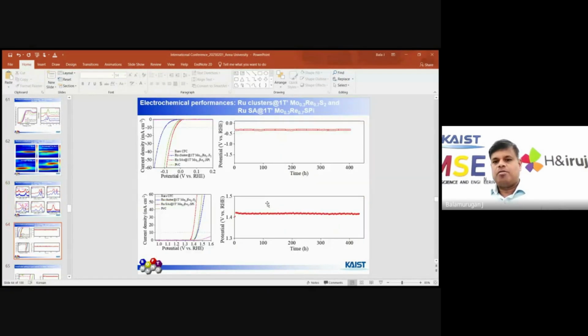And after confirming this material, we did the HER and OER performance. We can see the blue one is the cluster, and the red one is the single atom transformation. After single atom transformation, the overpotential drastically reduced, and the durability is highly stable, maintaining the potential for 400 hours. But in the case of OER, there is a lower overpotential compared to the cluster and the commercial catalyst, and high durability for 400 hours, even